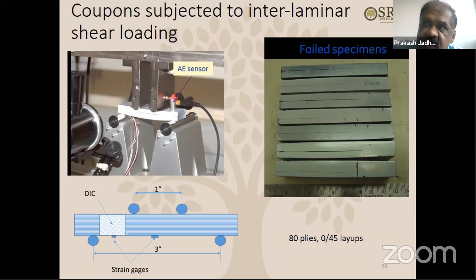Okay. So what it does is the movement of all these particles of paint along that surface, it tries to correlate subsequent images, the movement of particles, to the strain. Of course it has to be calibrated initially. So you calibrate, like you give the dimensions of a rectangle initially, and then as time moves, you can correlate the changes in the dimensions for every particle, and then you can find out the in-plane strain or interlaminar strain, x direction strain, y direction strain, and xy strains.